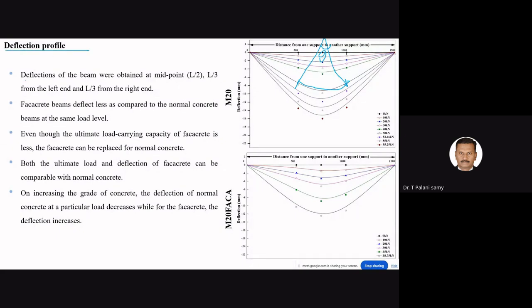The deflection profile. The deflection of the beam was obtained at midpoint, L by 2, and at L by 3 from the left end and L by 3 from the right end. So it is two-point loading, and at L by 3 distance we measure that deflection. The facacrete beams deflect less as compared to the normal concrete beams at the same level of loading. The facacrete beams deflecting less means there is very good bonding between these two, and some mechanical property is very helpful for the reduction of the deflection. Even though the ultimate load carrying capacity of the facacrete is less, the facacrete can replace normal concrete. Both ultimate load and deflection of the facacrete can be comparable with the normal concrete.